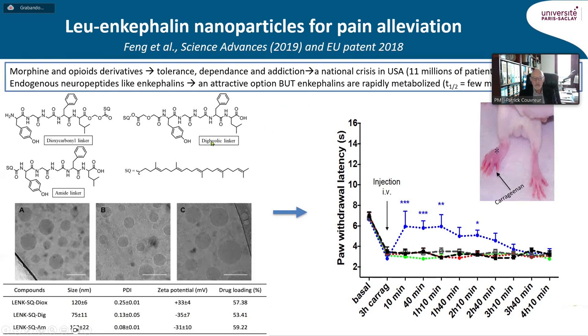And to overcome this problem, as you can see here, we have synthesized a small library of leu-enkephalin squalene bioconjugates using various chemical linkers, dioxycarbonyl or diglycolic or amide. And after putting those bioconjugates into water, you can see that we got once again nice nanoparticles with a size in between 70 and 120 nanometers.